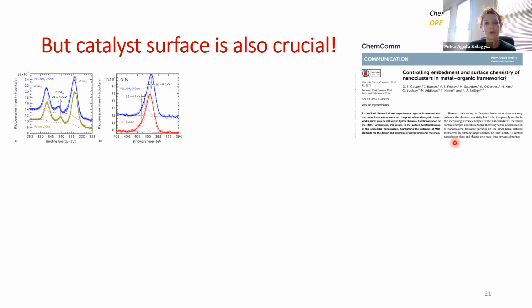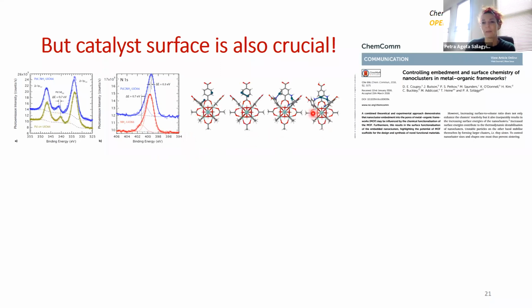And we were able to show that in this particular framework, there is a charge exchange between the palladium and the nitrogen of the amino group, some kind of charge transfer, which resulted in a partial oxidation of the palladium and a partial reduction of the nitrogen. So we can see that there is some kind of bonding between the two, and we could also rationalize it in terms of a palladium-nitrogen bond.